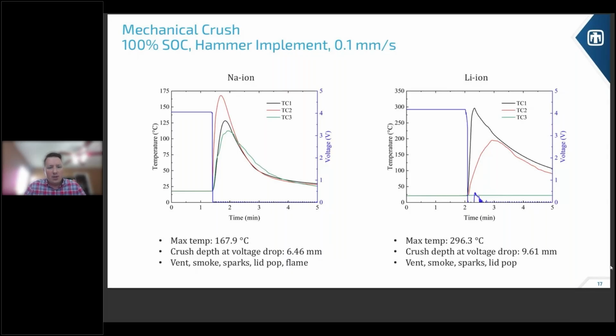So these are the quantitative results of that test. The right side is the max temperature of lithium-ion at 300 degrees C. So the lithium-ion in this case actually did get hotter. Sodium ion only got to 168, but they both had the same observable failure. They both had this venting, smoking, and the lid of the can popped off in both cases. Next.